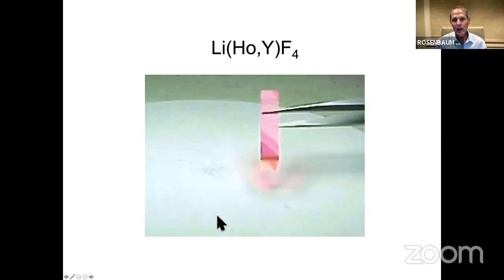So this is what the material looks like. They're beautiful single crystals. You can buy them in sizes up to centimeters because they're used as laser rods. When they're used as laser rods, they have a large mixture of rare earths. We're interested in just one rare earth, that is the holmium, which is held in the lithium tetrafluoride matrix. And you can do substitution by yttrium.